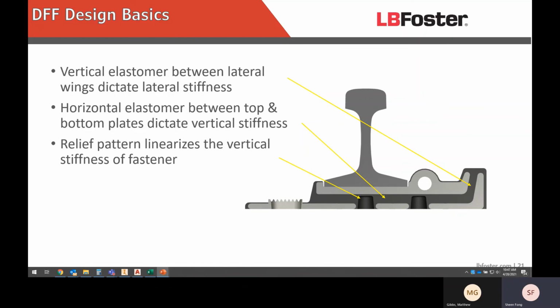So just some basics of a typical direct fixation fastener design. Here you can see a cross section of a typical DF fastener. You see there's a top plate that secures the rail and a bottom plate that secures the fastener to the plinth. The elastomer that is between the lateral walls, that's in a vertical orientation, that dictates the lateral stiffness of the fastener. And the rubber that is between the top and bottom plate in the horizontal orientation, that primarily dictates the vertical stiffness of the fastener.